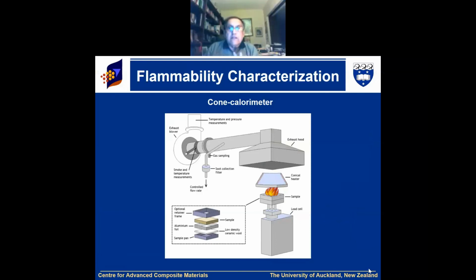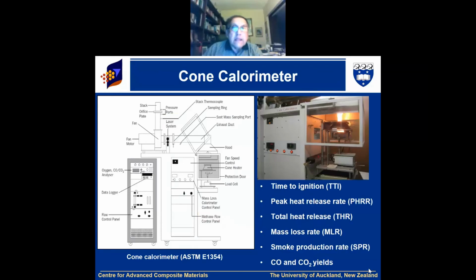And then if we look at the cone calorimeter, you have to hold the specimen, and then there is a heat source, the heat flux will be controlled, and it will burn. And also the exhaust hood will analyze the gas so that we will know carbon monoxide, carbon dioxide, smoke production. Also, I will show you the main outputs: time to ignition, peak heat release rate, which is one of the most important outputs, total heat release, mass loss rate, smoke production, carbon monoxide and carbon dioxide yield. And we have our own cone calorimeter, various parts are there. There's no point in explaining them.